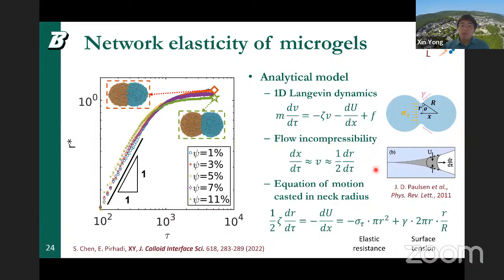And then a trick we do here is we can recast this equation in terms of neck radius by relating the velocity of the particle movement along the axial direction to the neck growth. This is considered by the flow incompressibility, where there's a relation developed by Paulsen that relates these two velocities together. These two velocities are orthogonal to each other, but there's a relation between them. So we can now recast this particle equation using the neck radius change. And we can see here, this radius change will be balanced by two contributions. One is the elastic resistance, where sigma is the stress in the neck region, and then the surface tension.